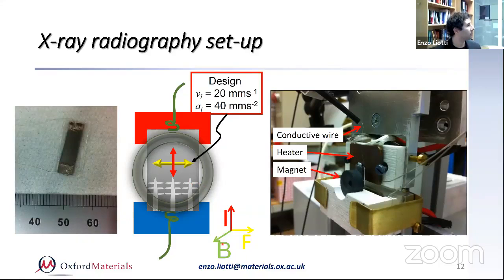And as you can see here is an example of how this little setup works. As I said, the B is the magnetic field that passes through the sample. I is the current that can be controlled because we use a pulse generator, so you can put different kinds of pulse in it. And then the yellow is the Lorentz force. In this case, if the magnetic field passes in the plane of the sample, so it's perpendicular to us, coming out from the screen, and the current goes up and down in this direction, then the Lorentz force will be in the other direction.